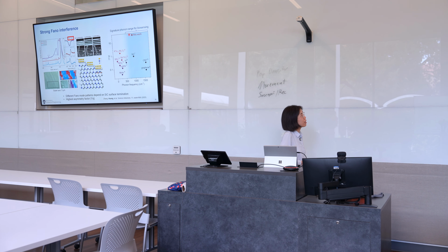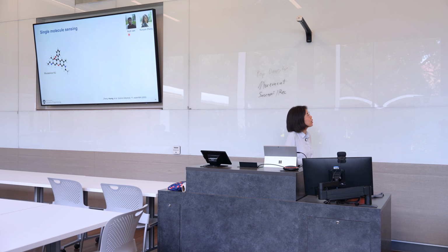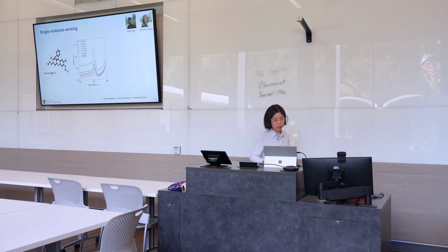So what's useful about this large quantum interference? Well, for one thing, it can be useful for sensing. Here, we demonstrated single molecule sensing using these phonon modes. We use a model molecule called rhodamine 6G. We deposited different concentrations of these molecules onto the 2D silver surface. You can see with the increase of concentration, the phonon mode has some changes. The intensity increases, the line shape is a little different. At the bottom, we have the pristine sample and solvent only. Pristine means nothing is done onto the 2D silver, and solvent only means just water, no molecule.